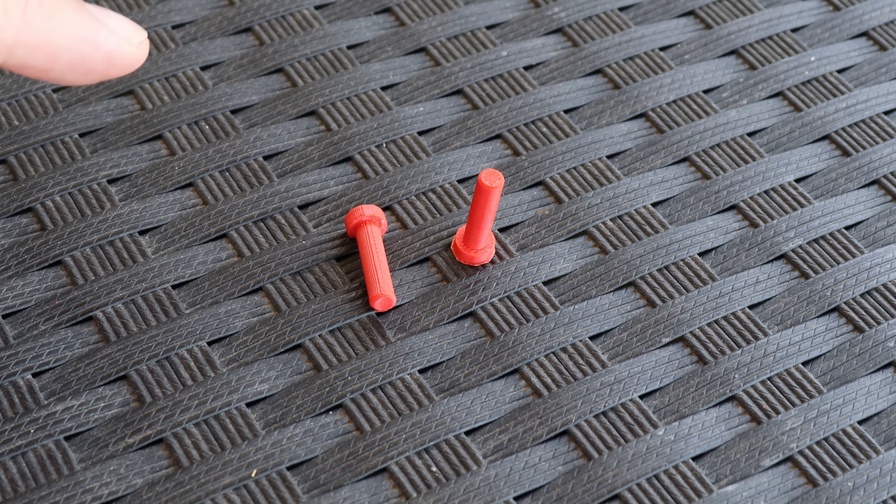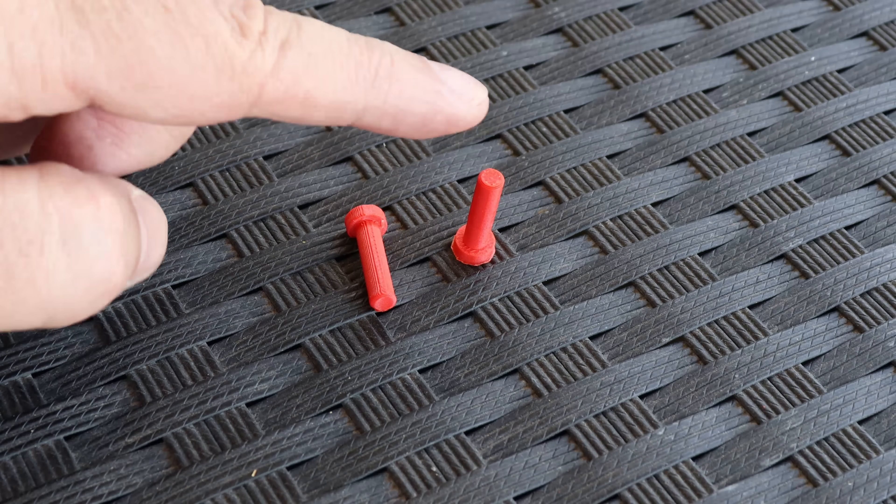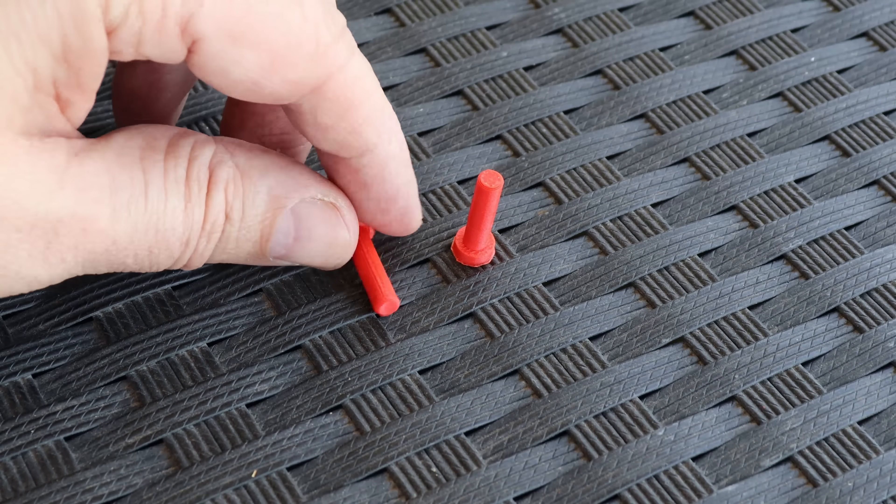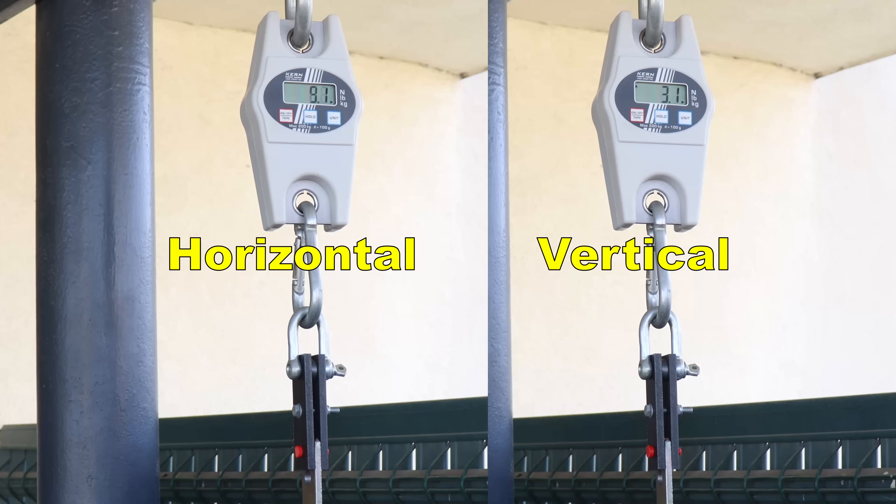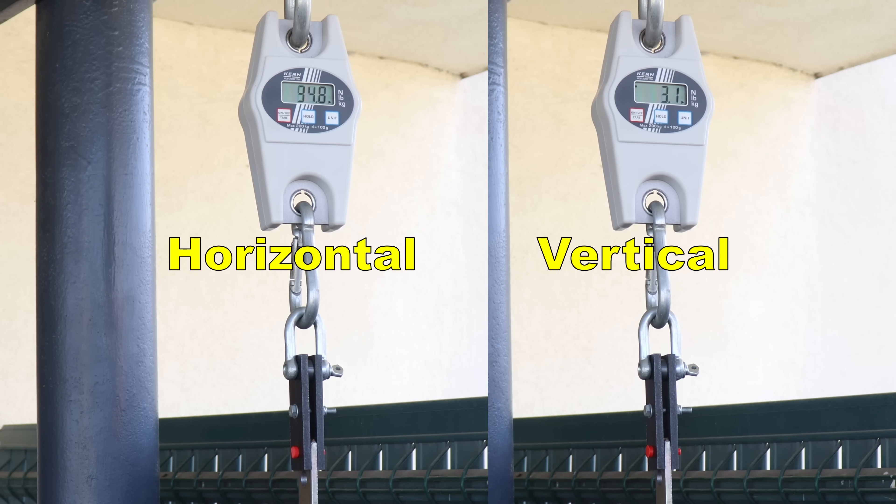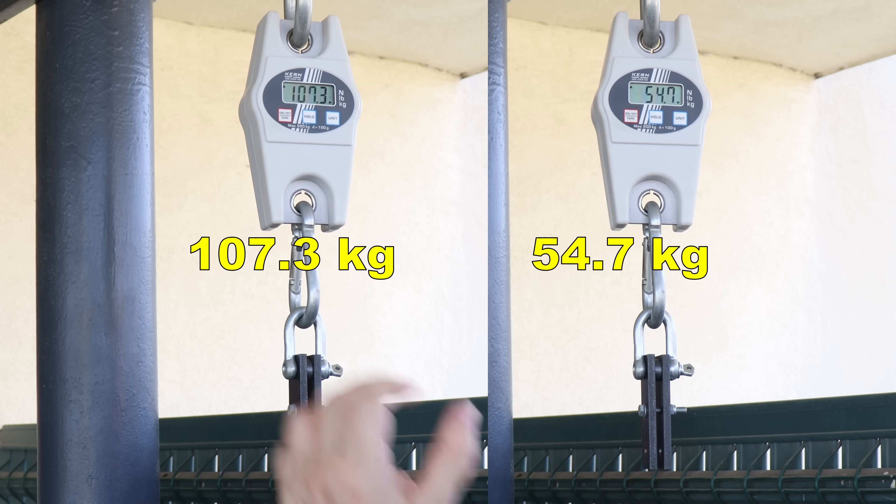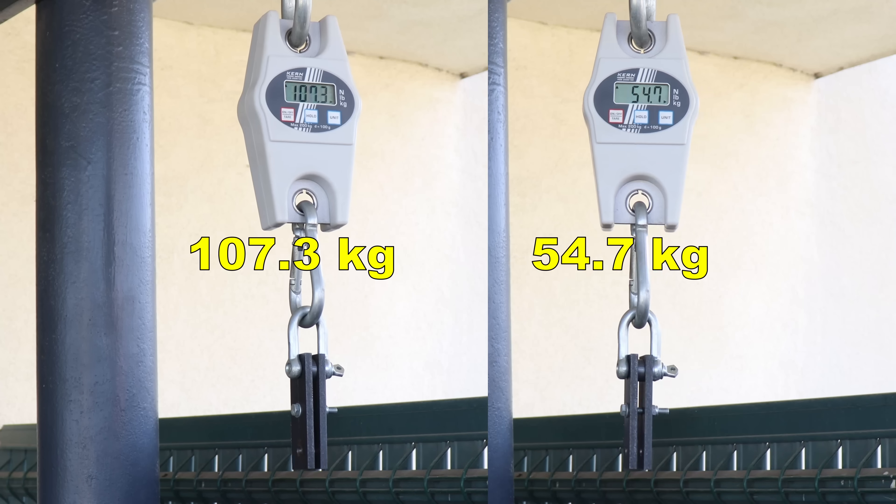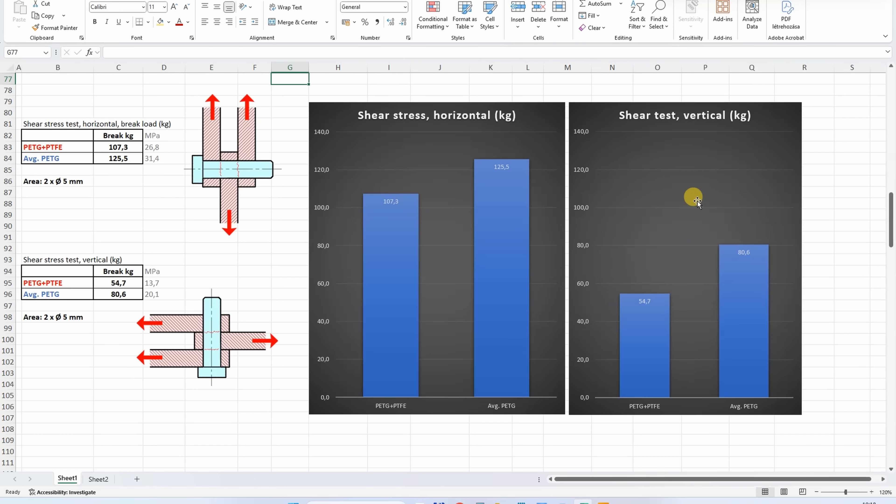Shear tests with horizontally and vertically printed test objects. And I am starting with horizontal ones. Side by side, horizontally and vertically printed test objects. In both tests, Spectrum was weaker compared to the average PETG. The horizontal test object is less sensitive to the settings, unlike with the vertical where the layer adhesion is very important.